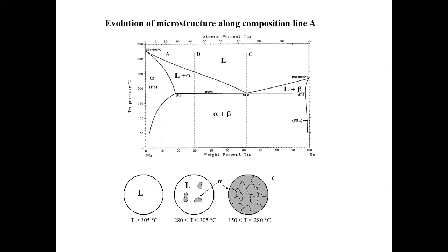It's lead dominant, lead rich. What is the number? The number is 10 percent tin. This is a composition line, and we have a right number on this. So we have 10% tin in the system, and we know that it's a homogeneous phase. So every single region of alpha phase will have this 10% of tin, mixed with 90% of lead. Did that make sense to everyone?